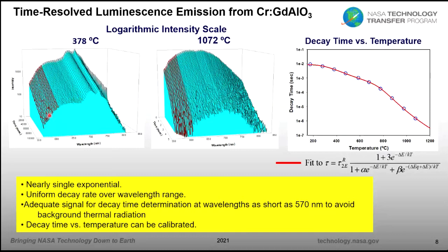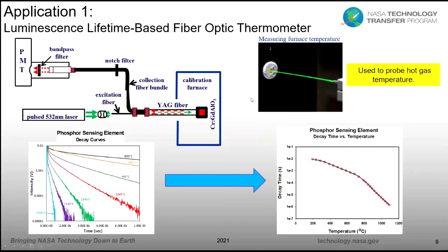If you didn't have that strong background, not trying to get to super high temperatures, then you could collect much more of the emission. Then at each temperature, you can determine the decay time and plot it versus temperature. And those are the points here. You can fit it to the equation I showed you in the previous slide. Shows a nice fit. And it shows two ranges of temperature sensitivity. First, the range from about 200 to 800 degrees C, where it shows more modest temperature sensitivity, not too steep a slope. And then for temperatures above 800 degrees C, you have more temperature sensitivity, as you can see by the steeper slope here.